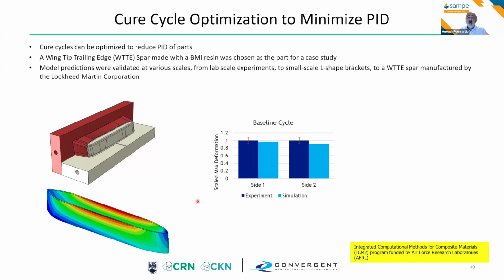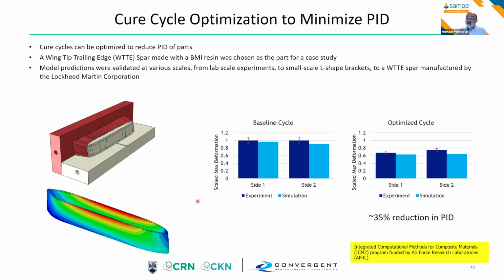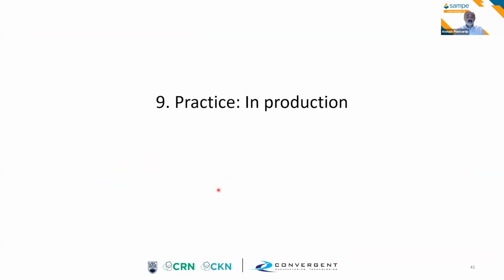And then what was done, the baseline cycle was modified to get the lowest possible deformation. And in fact, the simulation led to a 35% reduction in the process-induced deformation. Again, all the time as we try to share the capabilities of process simulation in industrial practice, we come up against the issue of proprietary information. So again, you're seeing a scaled, a normalized prediction here. What about in production? Where are we in production?